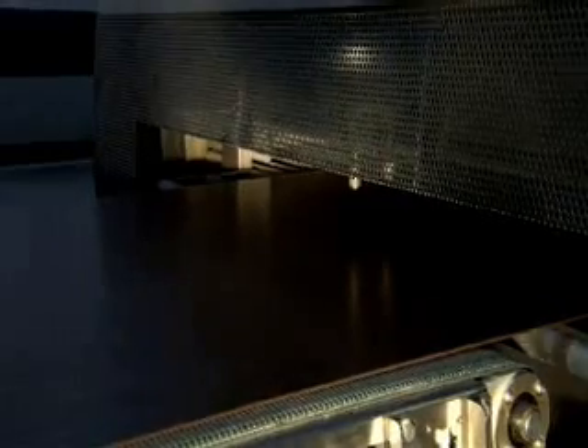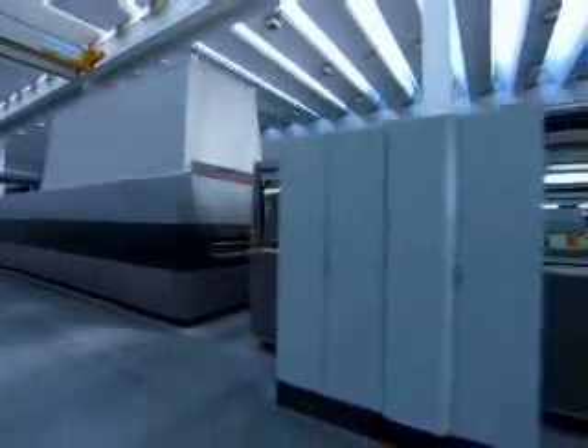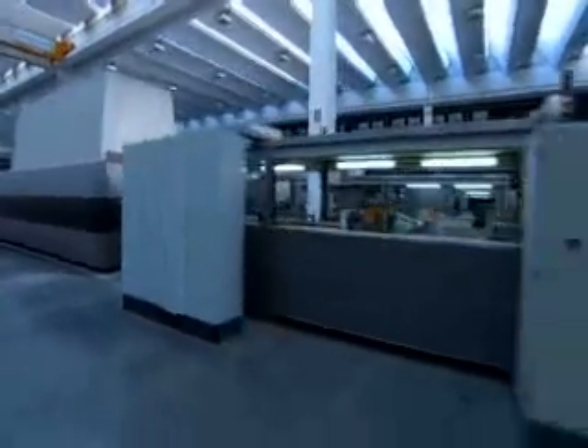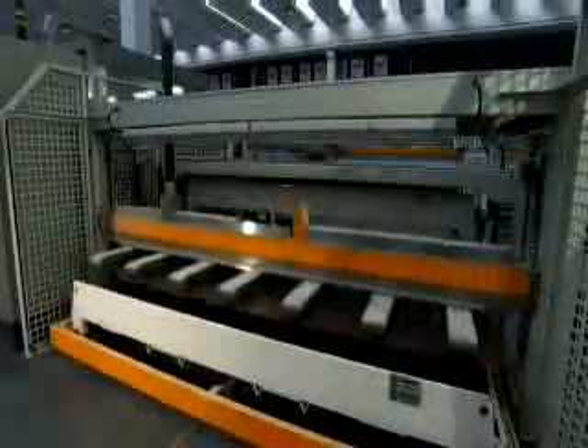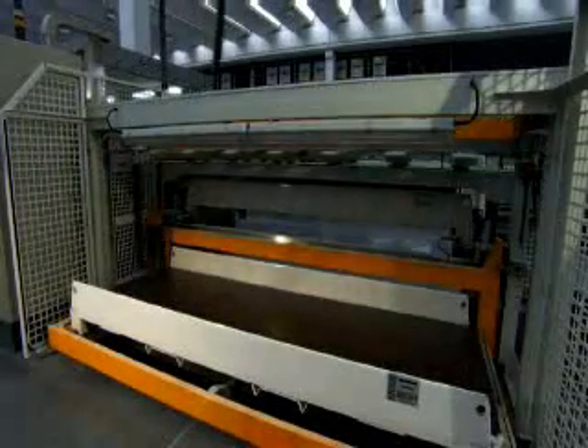The third and last phase is cooling. A combination of indirect and resistance cooling radiators make it possible to cool the slabs in a highly controlled way, completely eliminating the risk of inner stress. This is an aspect of fundamental importance for slabs of this size. At the furnace exit, a system called Qualitron BS performs quality control. Then the slabs are cleaned with soft brushes and unloaded onto metal platforms.